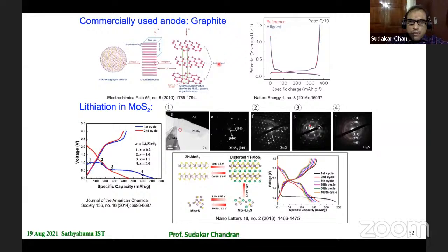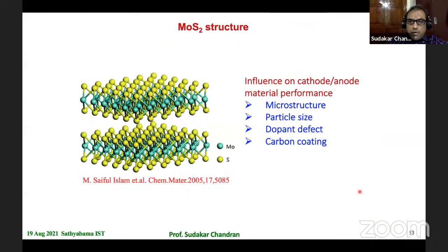Graphite, in fact, does not support that. Graphite is the typical anode that is used in lithium-ion batteries. It does not support it, and therefore people are exploring various other materials. Also the capacity of the graphitic or carbon-based anodes is somewhere around 350 milliampere hour per gram. But for example, molybdenum disulfide exhibits much higher capacity. The only problem is, as you keep on cycling, it goes down, and there is a structural change, and therefore one needs to understand how one can tailor it to make it suitable for lithium-ion battery application.